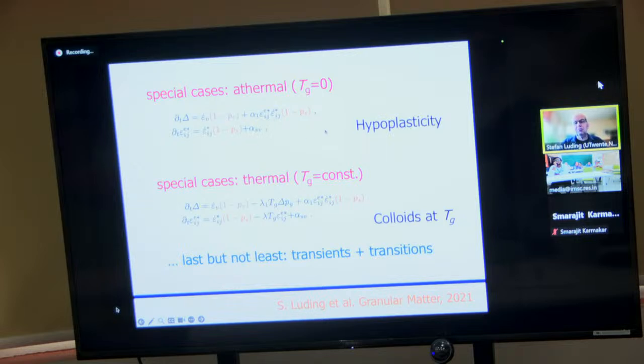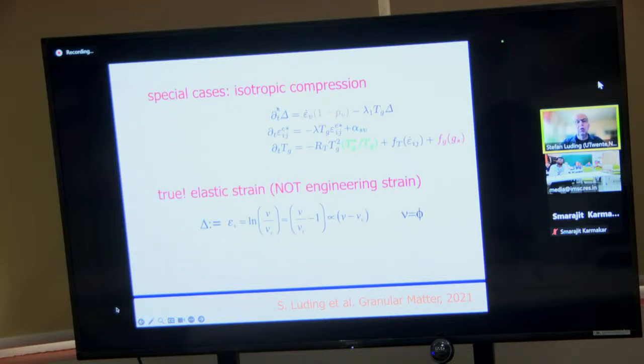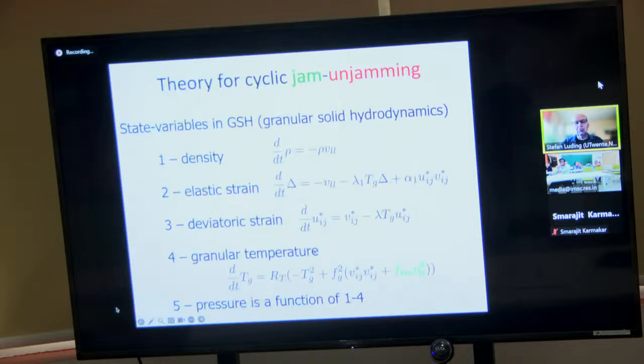Hypoplasticity is a special case. If I want, I can go to a limit of hypoplasticity. I can do colloids at finite granular temperature, or I can do isotropic compression, which I will do in the next minute, and I can define a large strain definition of the elastic strain. So you see, epsilon dot here is the total strain, epsilon_e is the elastic strain only. So that's the difference. You have total strain and elastic strain, and there's also a plastic strain, which I don't want to go into detail today. But anyway, this is the theory summarized in different words, the same as we had before.